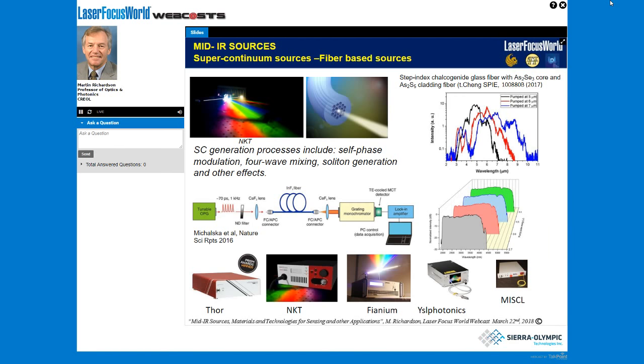Supercontinuum sources were first, of course, observed in propagation of ultrafast pulses, and particularly the propagation through optical fibers. Initially through glass optical fibers, but now in particular through hollow core fibers and fibers with optical structures that are designed to specifically maximize the supercontinuum generation. As I mentioned before, the supercontinuum generation can come from a number of different processes: self-phase modulation, four-wave mixing, soliton generation, other effects. And what's shown here is a couple of notable recent results.